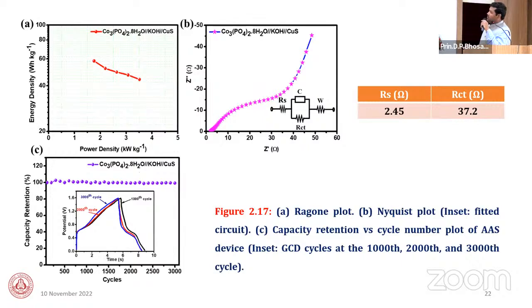The energy density and the power density of this device is 58 watt hour per kg at 1.5 kilowatt per kg power density, and the cyclic stability of this device is 94% capacitance retention after 3000 GCD cycles.